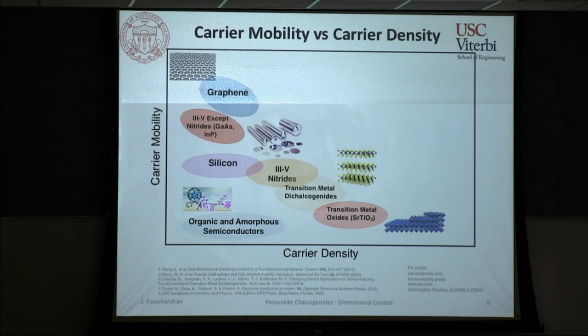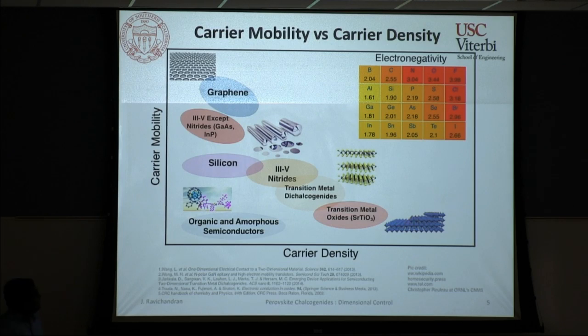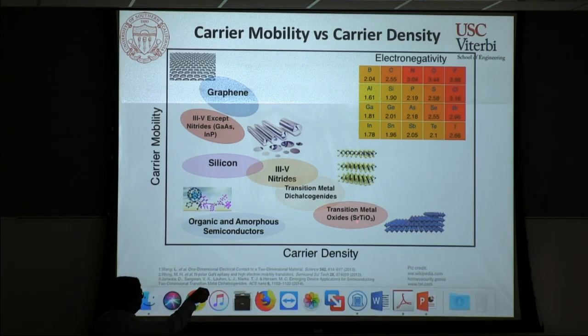So one way to think about this is, let's take this case of strontium titanate, which is a very nice semiconductor material with d-band conduction. If you take this system and somehow maintain the framework that is present here, and look at the interaction between the d-band conduction that arises from the B site element and the anions, these two elements tend to have a very large electronegativity difference, and hence the interaction between these gives rise to strong scattering of electrons